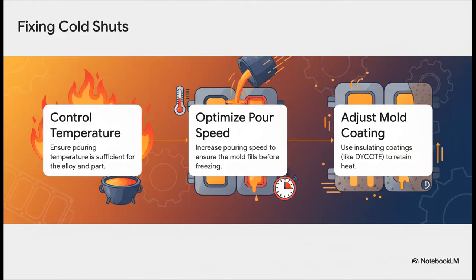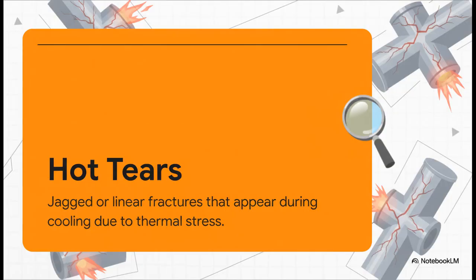So, the fix? We crank up the heat and the speed. Keep that aluminum melt in the sweet spot, generally above 650 Celsius. Pour fast enough to get that cavity filled up quick. And here's a great pro tip. Using an insulating mold coating, like DYCOTE, can act like a little thermal blanket, keeping the metal hotter for longer as it flows.